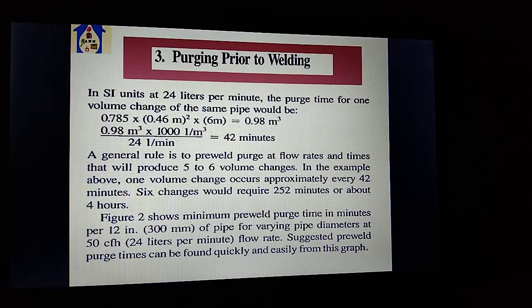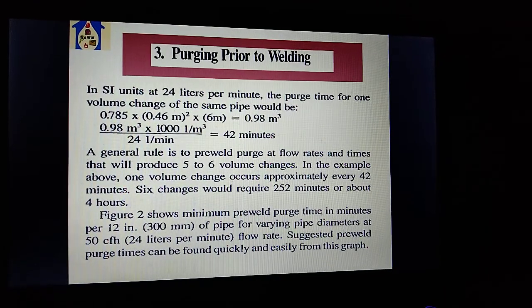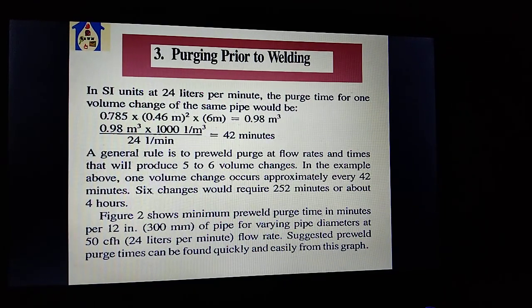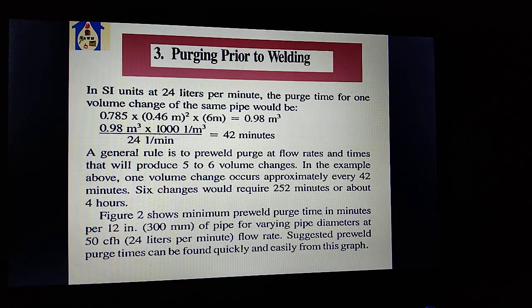A general rule is to pre-purge at a flow rate and time that will produce 5 to 6 volume changes. In the example above, one volume change occurs approximately every 42 minutes. Six changes would require 252 minutes, or about 4 hours.